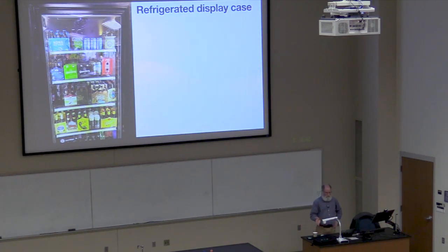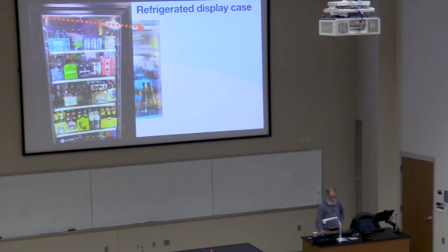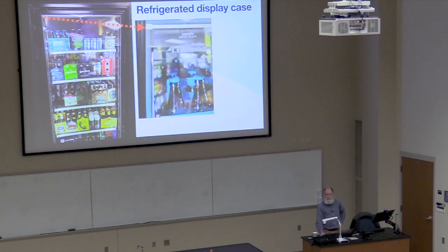Refrigerated display cases. You probably don't notice those like I do. But I was in a convenience store and I found this case. And I took this photo because the lighting was just right. I wanted to get a photo of that upper left corner. If you look up there, you'll see a silver bar across there. That's because this glass has a tin oxide coating on it. And our customer takes that glass and they apply this silver bus bar, and then they heat it up, fire it, make it hard. And then each of these little refrigerator doors has a little power system. So once again, you can run current through there, heat that glass so that when somebody opens it, looks inside, and the humid air gets in, the humid air doesn't condense on that surface.